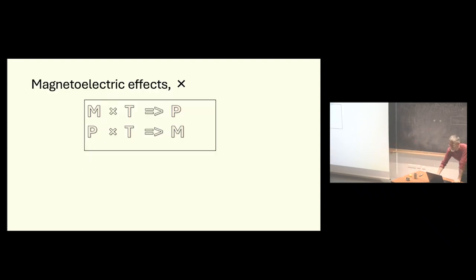So whenever you have in parallel 2 vectors of different kinds, which you can find in here, there is always the third one which is also present because the symmetry allows only this. Either you have only one irreducible representation which is broken, or you have triplet, or you have all of them, which is also sometimes useful when thinking about phase transitions, magnetoelectric effects, electromagnons, etc. Okay?